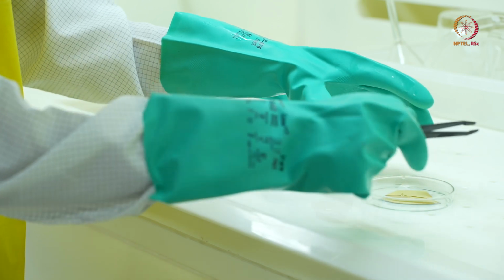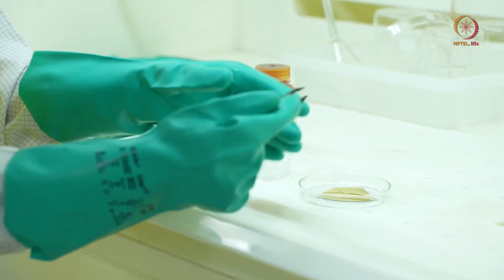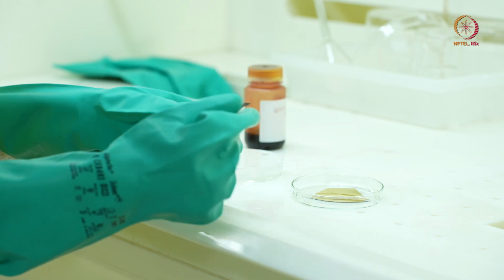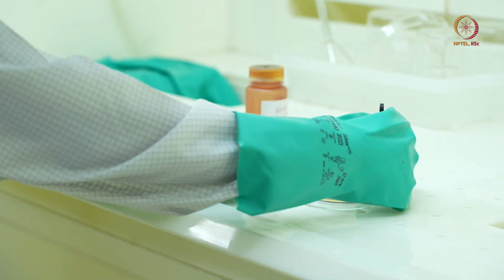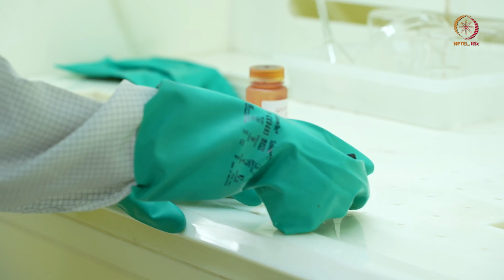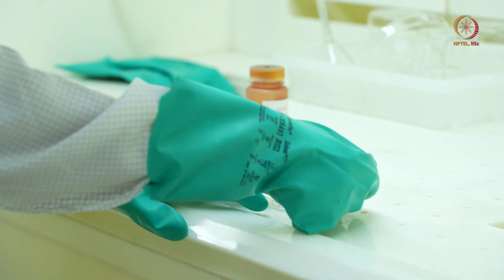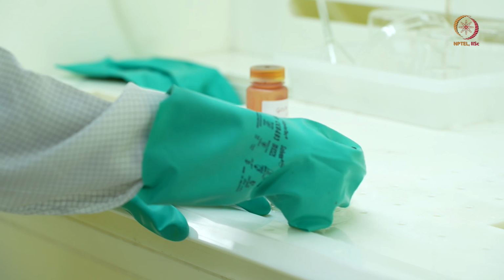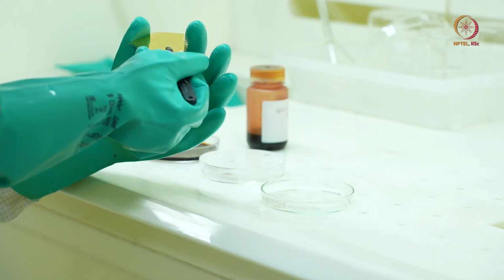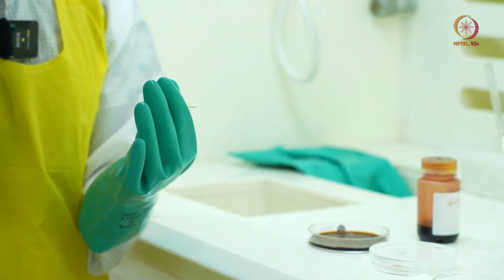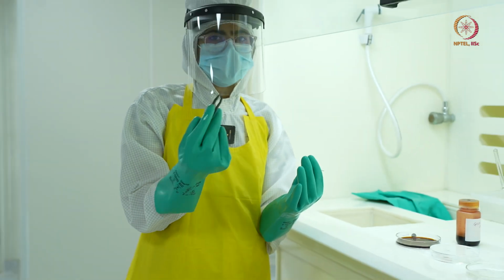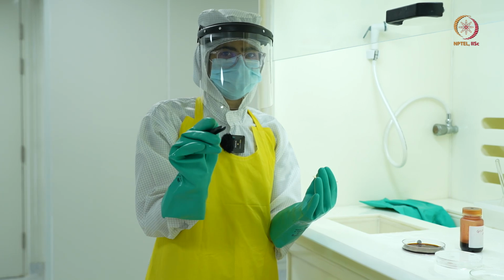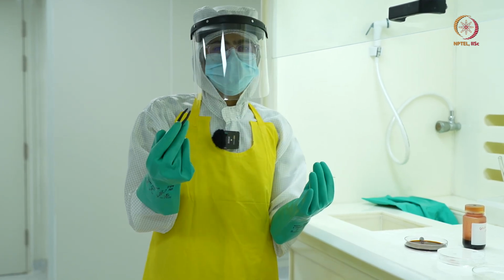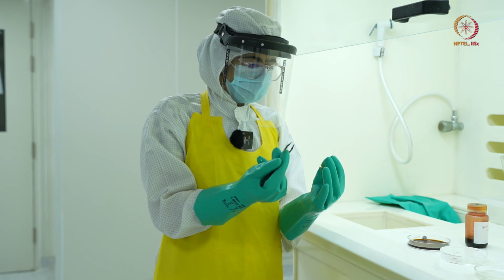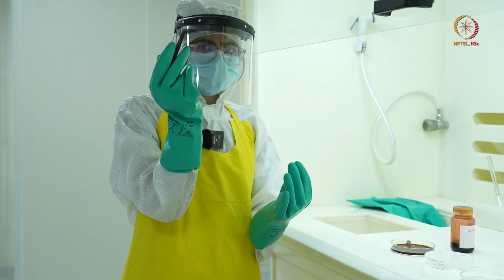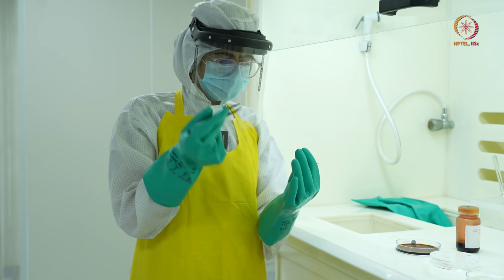And I have my sample in this petri dish. This is a gold coated sample. I have coated 200 nanometers of gold onto it. So this is a glass wafer and I have coated gold onto it. And one more thing, as you might be seeing, this is a plastic tweezer. When we are dealing with acids, we should ideally use plastic tweezers because metal may corrode when we are dealing with acid. So I am using this plastic or polymer based tweezers.